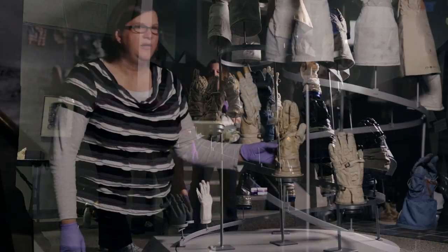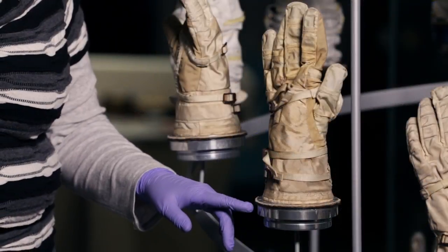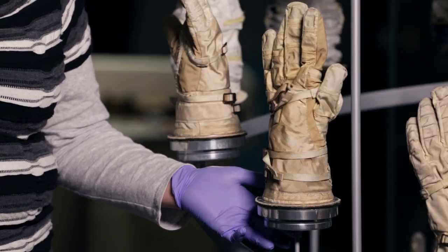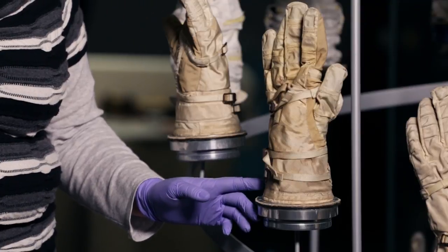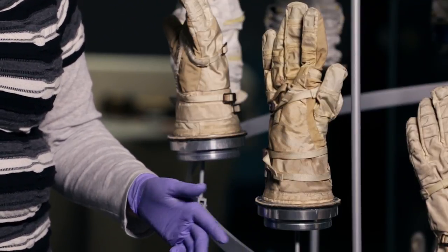One of the most difficult preservation issues we have with gloves is the Gemini time period. The materials they used were very sensitive and are not aging well. The exterior nylon, which used to be a light cream color, has darkened to yellow due to light damage from display and storage over time. The other problem is that the aluminum alloy wrist disconnect, which is at the bottom of the glove, exhibits advanced signs of aluminum corrosion.